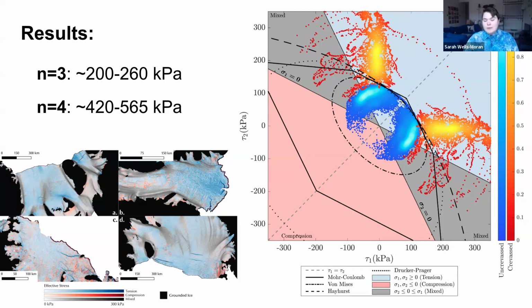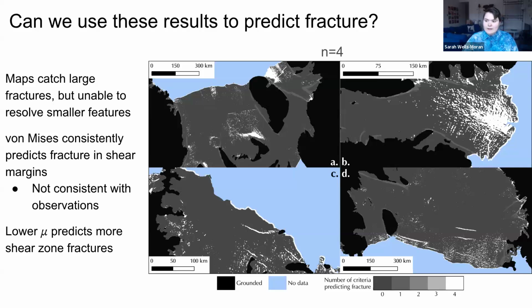And so then we decided to see what would happen if we applied these yield stresses to all of Antarctica. So this is what that looks like. And the thinking behind this is, can we use these results to predict fracture? These maps are really good at catching large-scale fractures, but they're not as able to resolve smaller features. What's really interesting is this gray area right here shows that 3 criteria say that this shouldn't be fractured, and 1 criterion says that it should be fractured. And the 1 criterion here is the von Mises criterion. So the von Mises criterion over-predicts fracture in these shear regions. We can see there are some areas where all of them are predicting fracture, but there isn't fracturing observed.